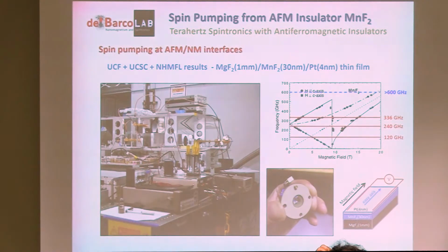All right, so we have tried exactly the same thing, a slightly different approach, but exactly the same material and heterostructure. Indeed, we tried first with manganese difluoride, a thin film, molecular beam epitaxy grown on top of magnesium difluoride, a bulk substrate. That is because there's an incommensuration between the lattices, but they're close. And then we deposit 4 nanometers of platinum on top of it. And then we went to the